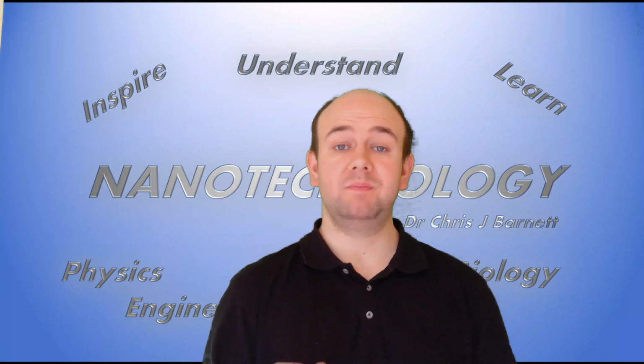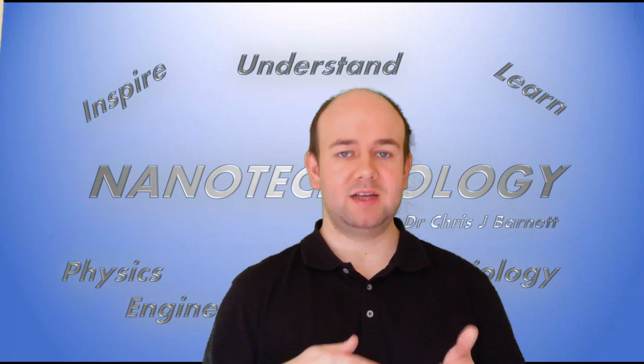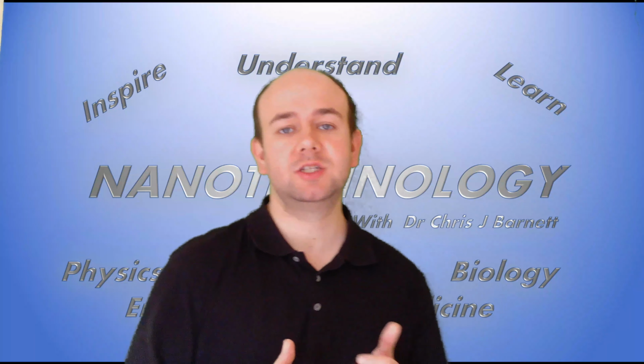What we did is we used an instrument called the nanoprobe, which we have at Swansea University. It allows us to position probes, or very sharp metal tips, onto nanostructures, and above it is a scanning electron microscope which gives us nanometer resolution to position these tips precisely and make sure we land on specific parts of nanostructures.